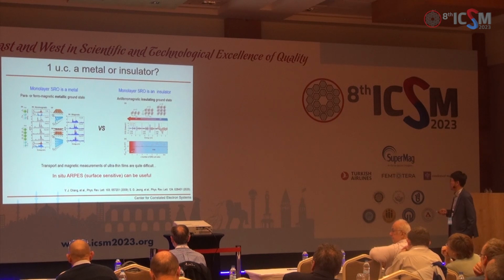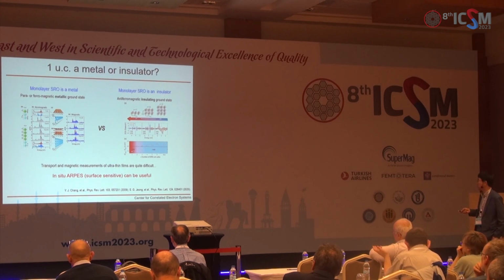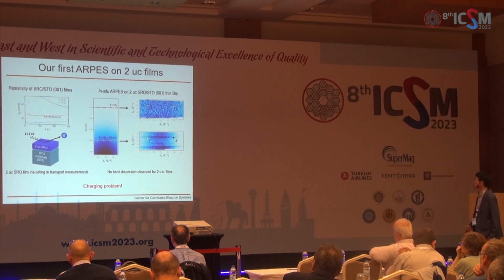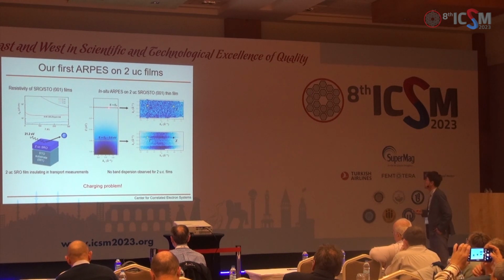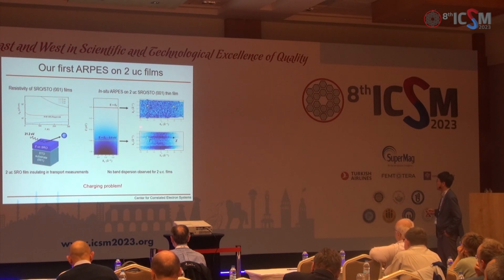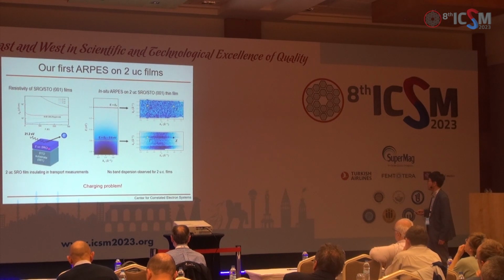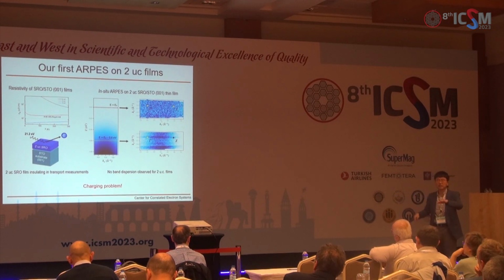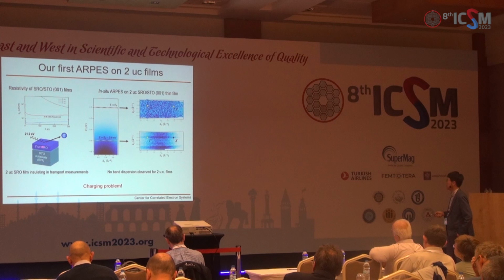Here, in situ ARPES can also play a role in resolving this issue. Initially we tried a very thin film, only 2 units, but we couldn't get proper data, and it turns out there was a charging problem in the photoemission process. In photoemission we shoot photons and kick out electrons, so these electrons, or the charge, should be compensated from outside. However, in this 2-unit-cell film, because of the step edges, they are broken pieces, so supplying these electrons is not possible in these ultra-thin films.